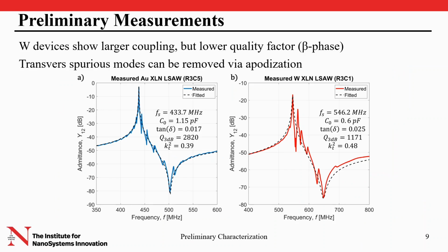After fabrication, we have a direct RF probing preliminary measurement of the devices, and we can see very good quality factors and coupling. In particular, if we look at the tungsten device, we see larger coupling but lower quality factor. This is because we employed a lift-off process that necessarily uses low temperature deposition, which produces beta phase for the tungsten, whereas alpha phase is much less resistive but requires high temperature, thus making it impossible to perform the lift-off. We also see some transverse spurious modes that can only be addressed through optimization of the fingers.